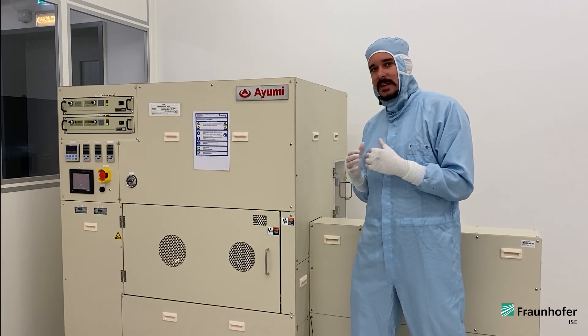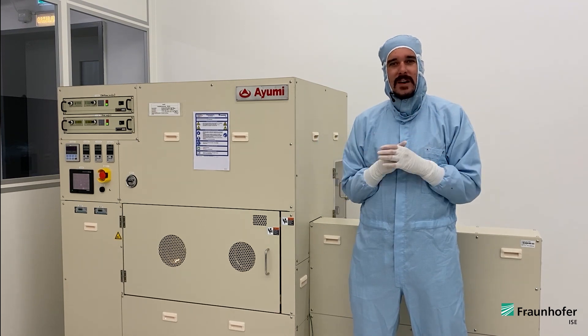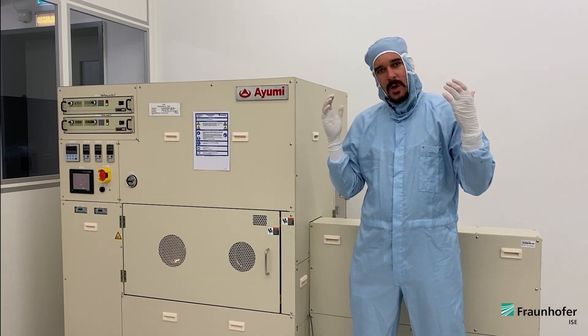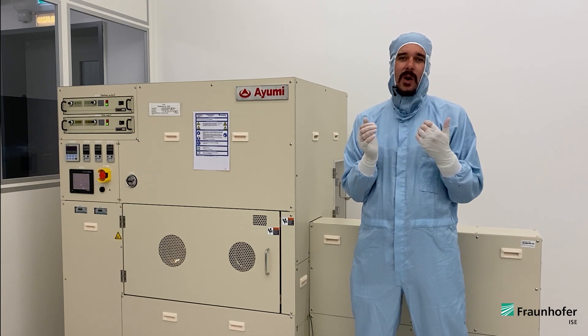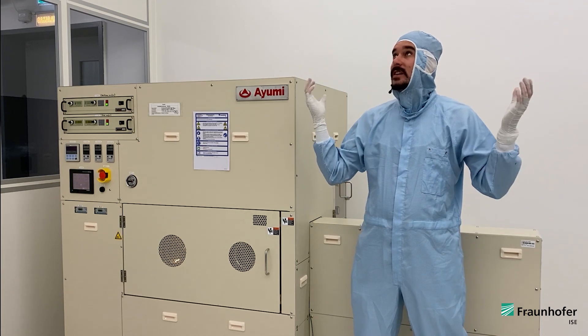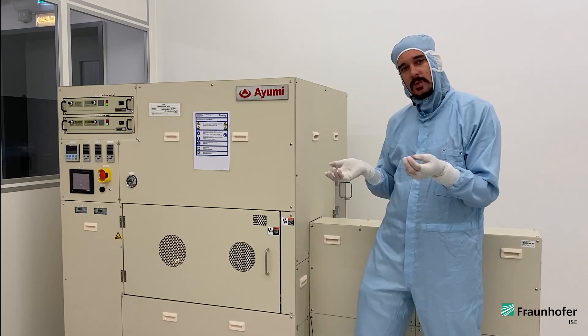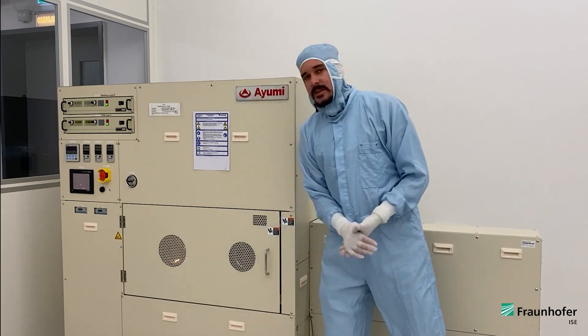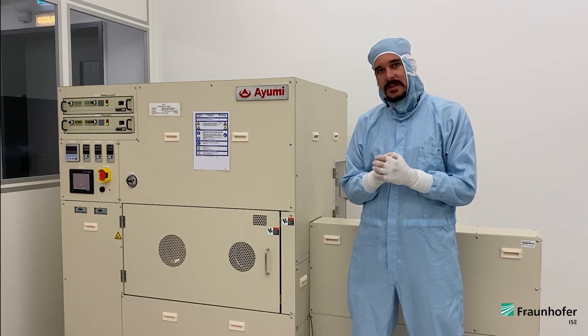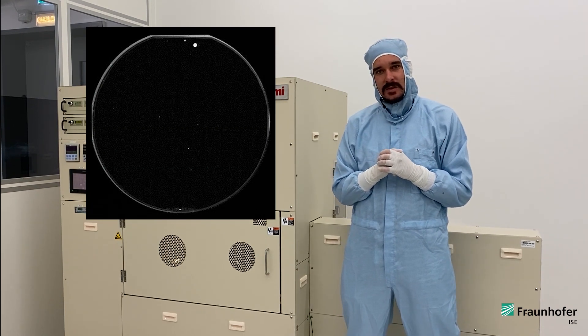For mechanical stability, it is mainly important that the wafer surfaces are very flat and that there are virtually no particles on the wafers which would prevent close contact. This is achieved by chemical and mechanical polishing performed prior to bonding, and also by working here in this cleanroom environment. We achieve fully bonded 4-inch wafer pairs, as we can see here in this image taken by scanning acoustic microscopy.